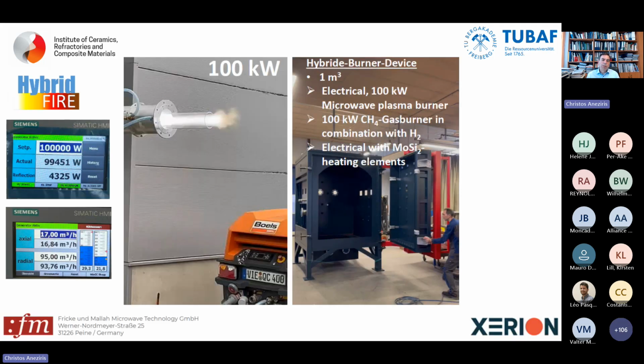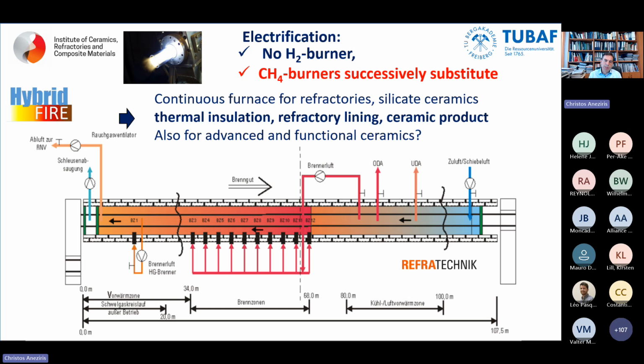Somebody would say, have you already done experiments with 100 kilowatt? Yes, it's working. And the most important is we will have a 1 cubic meter chamber, so we have the same volume, and we can see the electrical efficiency on the one hand, and on the other hand the quality efficiency, because the atmosphere has other radicals which can interfere and also change the quality of our products. Where do we want to go in terms of the projects? The positive results have to be transferred to a continuous furnace, something like 100 meters long, where normal refractory or silicate ceramic products are sintered. Of course, we have to keep in mind, it's not only the ceramic product which has interactions with the atmosphere of the different heating processing routes, but also the thermal insulation as well as the refractory lining.